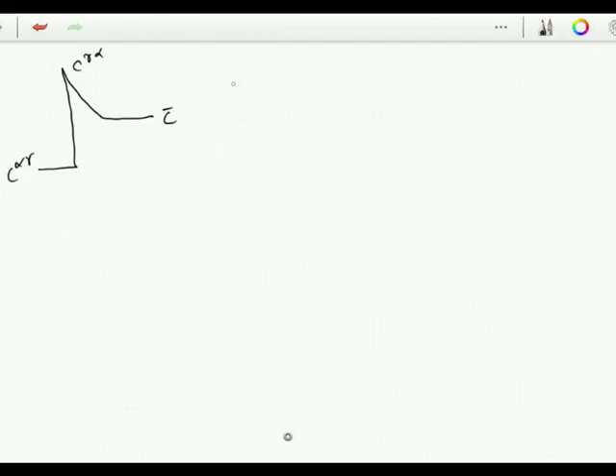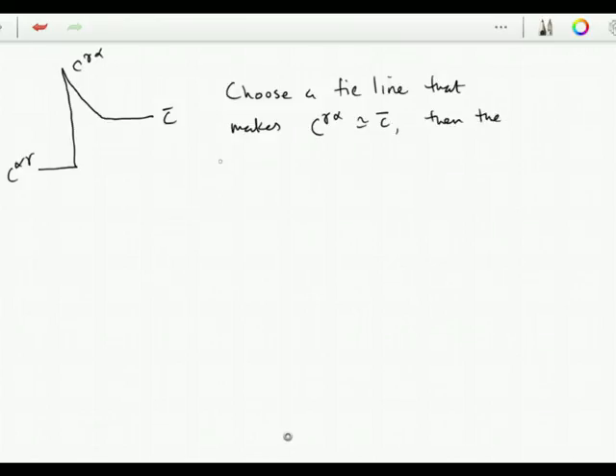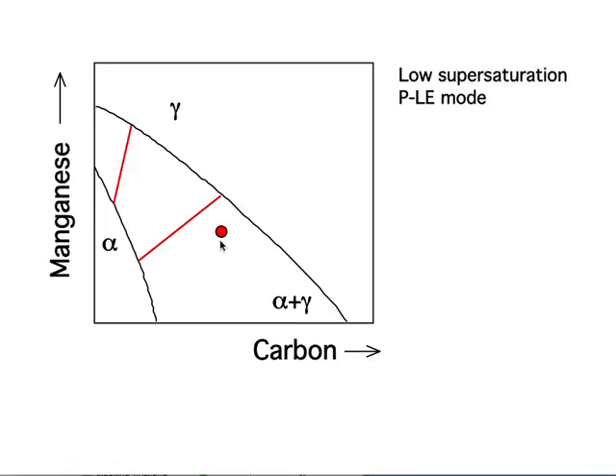So if I choose a tie line that makes C gamma alpha approximately equal to C bar, then the gradient becomes flat, like so. C bar, C gamma alpha, and C alpha gamma. So carbon is on the horizontal axis. So if I want the carbon concentration of the austenite to be the same as that in the alloy, then I draw a vertical construction line through that alloy composition, and where it touches the gamma phase boundary defines the tie line.